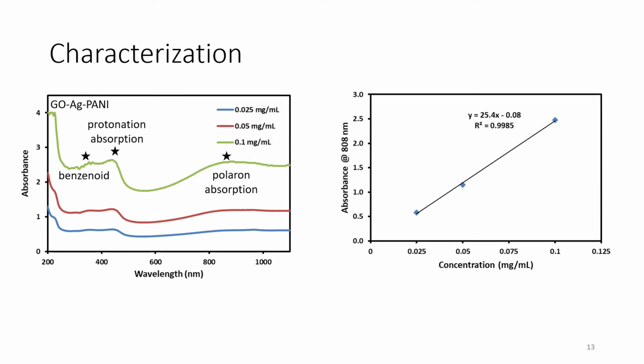Characterization of our ternary nanocomposite. This one is UV visible spectra of the nanocomposite at various concentrations. This is a typical UV visible spectra of polyaniline, including benzenoid, protonation absorption, and polaron absorption bands. Also, the concentration and absorbance at 808 nanometers is highly linear, which indicates good dispersion stability.